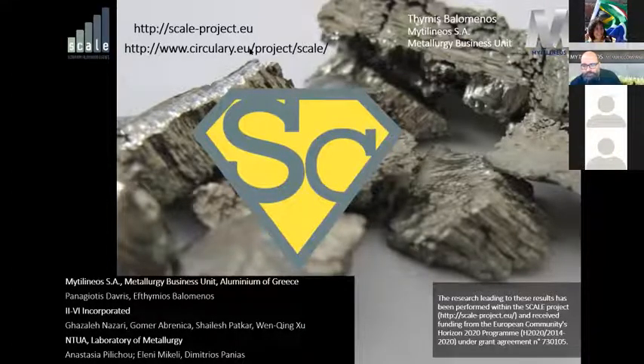And also you would be increasing dramatically the productivity of an alumina plant, right? Because we are now feeding it with mineral concentrate, the bauxite ore at best has 60% alumina and 20% iron. And at a lower quality, it has even more iron. So nobody has succeeded on an industrial scale to beneficiate iron out of the bauxite without smelting it, with beneficiation technologies, because bauxite has very fine particles and it doesn't seem to work.